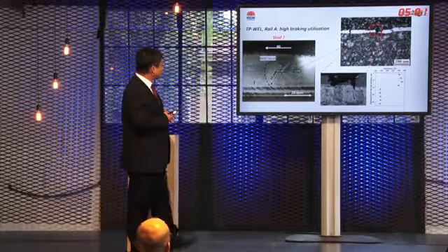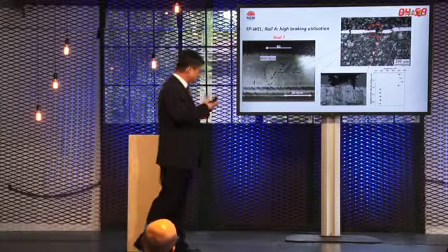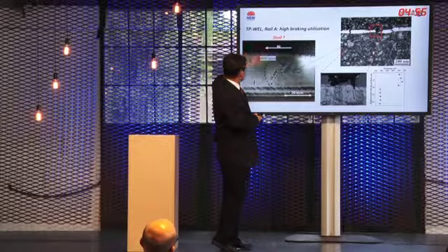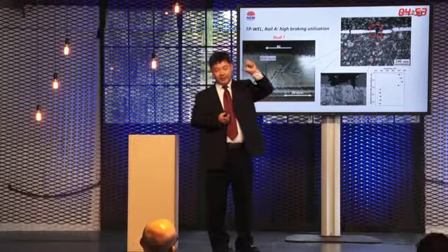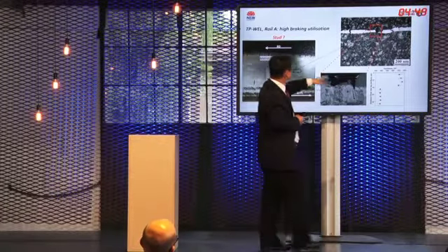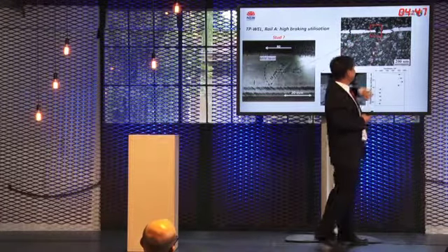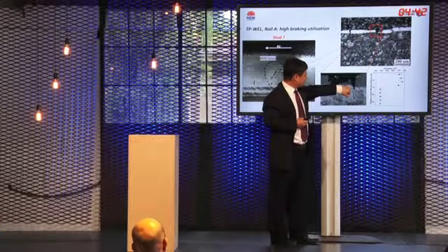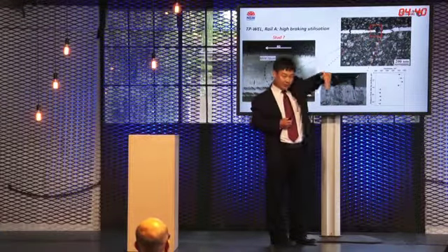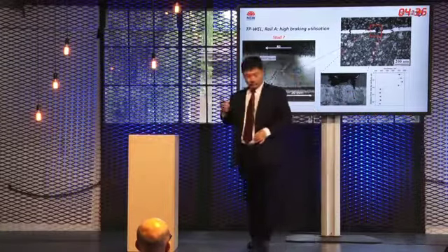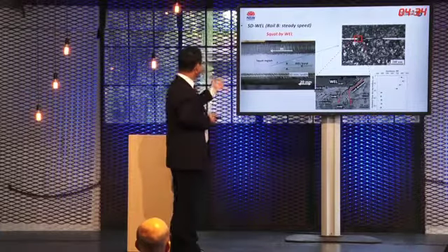We try to identify this by microscope. You see here, for the TP WEL, it's thermally induced and very thick, 50 micrometers. It's easy to break inside the white etching layer. Then the crack goes down. You see this direction. It's going down, vertical, because there's no texture.